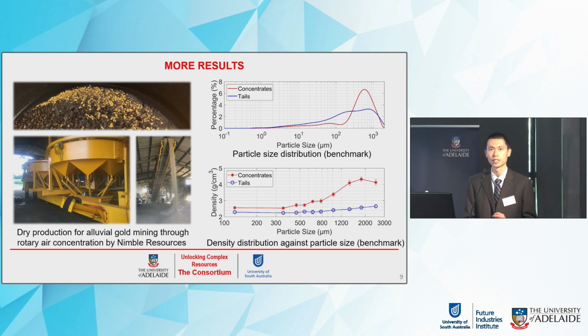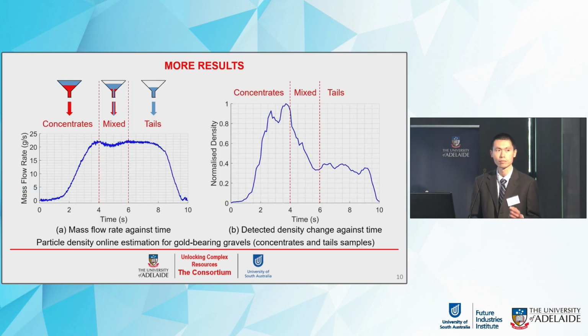Nimble Resources has their unique dry production for alluvial gold mining using their rotary air concentration. They are looking for something that could monitor the density of particles in the concentrates. So why density but not size? This is because the concentrates and tails have large portions of particles within the same particle size range. So looking at the particle size does not help. Instead, if we look at the density distribution against particle size, then the concentrates and tails are very different. So now the question is, can our sensor monitor density?